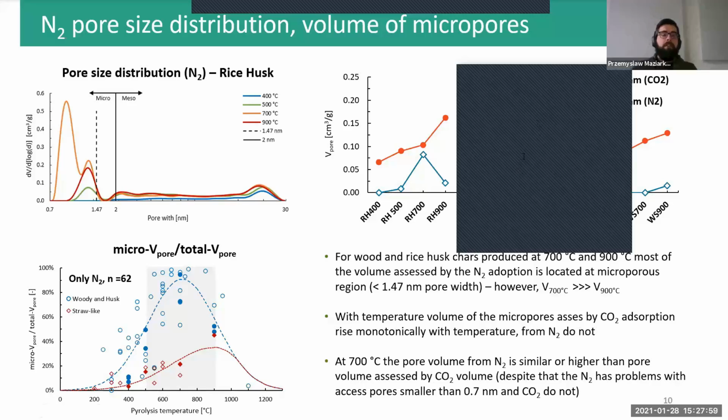Yes, of course. We also have to keep in mind that around 700 degrees, thermal degradation of the inorganics can happen. Below that temperature, we can also have within the biochar organic metallic compounds, like salts and such, organic salts, which can also degrade with temperature and produce inorganic materials which have totally different morphology and can also change the specific surface area that we would like to observe.